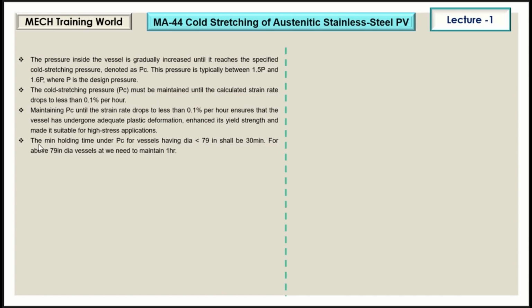So I need to confirm one more point with you. The minimum holding time for your cold stretching pressure, for vessels having a diameter less than 79 inch, shall be 30 minutes. So whenever the diameter is less than 79 inch, we need to maintain pressure for a minimum of 30 minutes. For above 79 inch diameter, we need to maintain it for 1 hour. This is the general timing followed by most industries, and the code also gives the same timings in the code book. So I request you to please refer to Mandatory Appendix 44 for a clear understanding of these points.